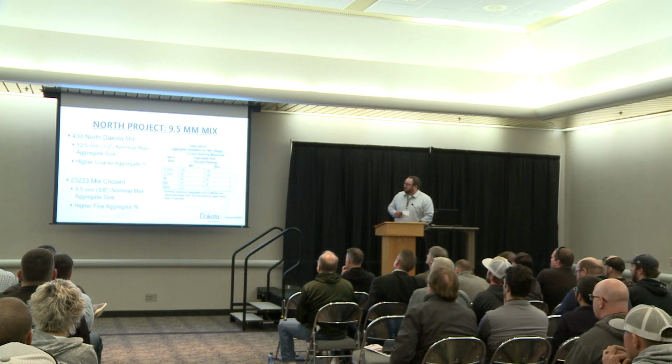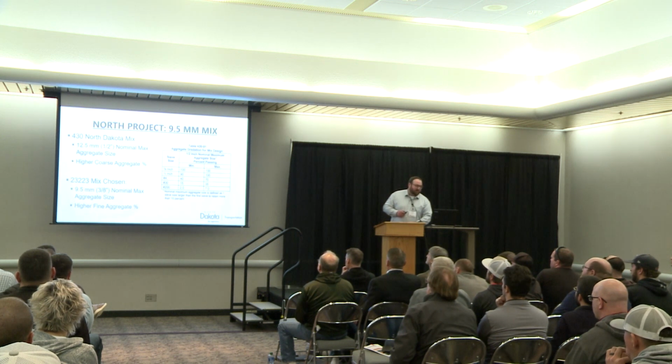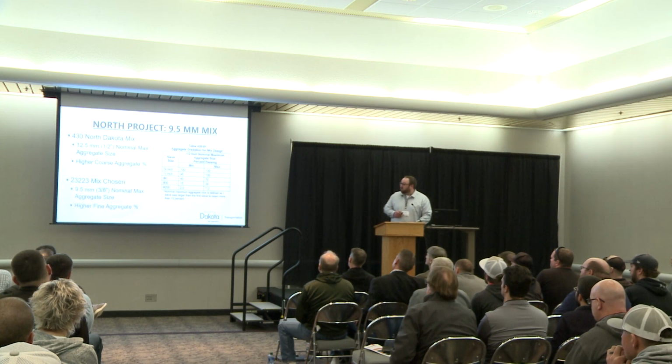So the differences between the 9.5 and our regular 430 mix. Our regular 430 mix, we run at a nominal max aggregate size of 12.5 millimeters or a ½ inch. So what we're doing is decreasing the nominal max aggregate size, which really means we have a higher fine aggregate percentage.